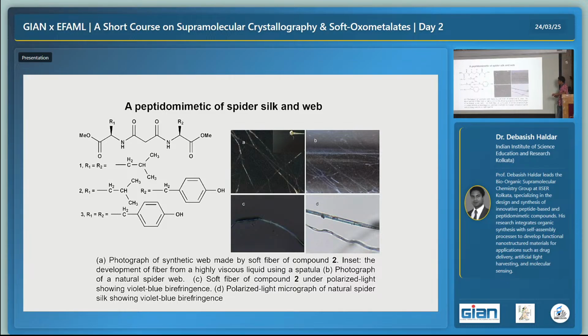Then we developed this compound, a peptidomimetic. The compound contains 2 amino acids, one is leucine and another is tyrosine, and this is a diacid. We put both leucine or both tyrosine on both sides of the diacid, and in a third compound we put leucine on one side and tyrosine on the other. With leucine the compound is completely crystalline, so we have the crystal structure. With tyrosine the compound is a liquid, but when we put leucine on one side and tyrosine on the other, the compound is a highly viscous material above 20 degrees centigrade, but below 20 degrees centigrade it can make a kind of fiber.